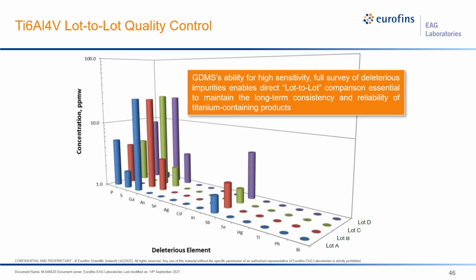Here, I give you an example that GDMS can be used very effectively for lot-to-lot quality control. Here we have 4 lots of titanium aluminum vanadium. You can see that, in spite of being produced in the same manufacturing process by the same manufacturer, they can experience variation in terms of the type of impurities and the content levels.